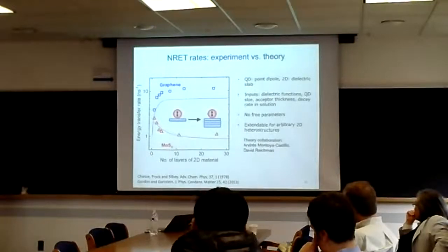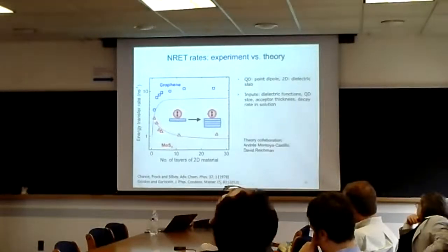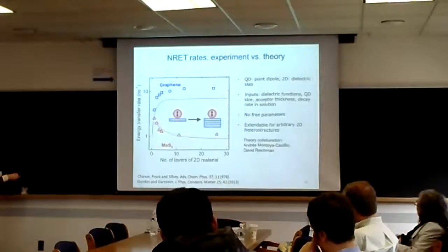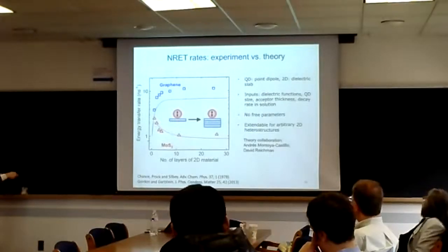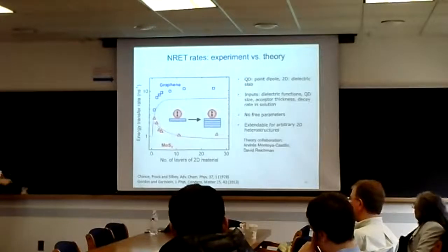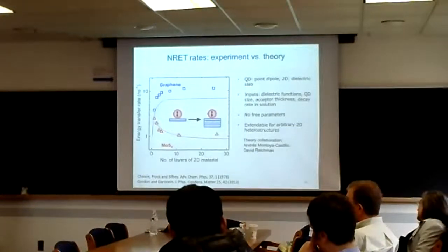In this COMSOL simulation, we are not including the shell effect and so on. There are reasons why this is obviously not exactly agreeing with theory, because there's 5 nanometers of zinc sulfide shell, and then a nanometer of ligands, and only then are you seeing your high dielectric, so to speak. So you're right that it does change the radiative properties, or the Fano effect, but the primary effect here for the change in the recombination rates is actually not radiative in nature.